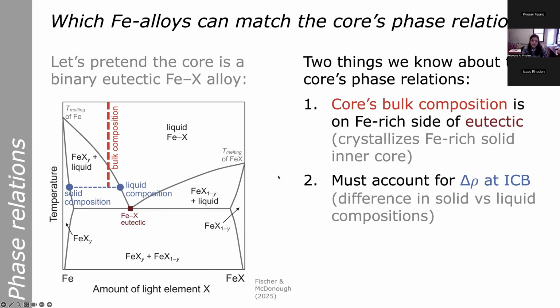And then the other type of constraint we get from mineral physics is to look at the phase relations of the core alloy. So if we pretend for a moment that the core is just a binary alloy, just FeX, where X is some light element that has a eutectic behavior, just for the sake of visualizing this, we can draw this cartoon phase diagram in temperature composition space for this eutectic melting. There are two things that we know must be true about the phase relations of the core alloy. The first is that the core's bulk composition, shown by this red dashed line, has to be on the iron-rich side of the eutectic composition, which is this darker red square.